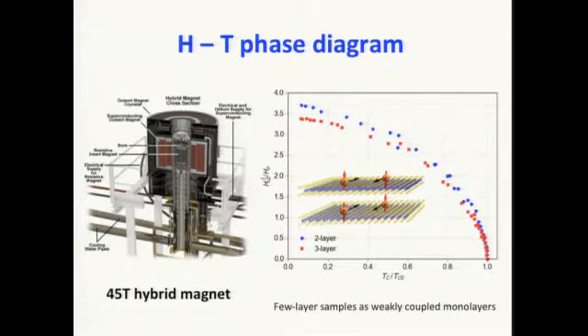The reason is that the interlayer coupling energy scale is much smaller compared to the intralayer spin-orbit splitting energy scale. So in that limit, the layers are basically decoupled. For example, I give some numbers here. The interlayer interaction is probably on the order of 10 meV, but the intralayer spin-orbit splitting, at least at the K and K prime pocket, is about 100 meV, the spin splitting. So in this case, you can think of the two layers as basically decoupled.